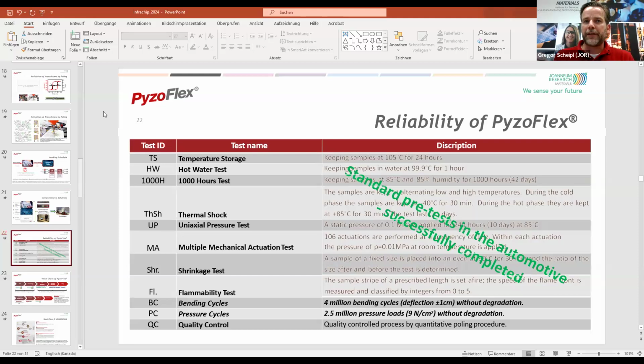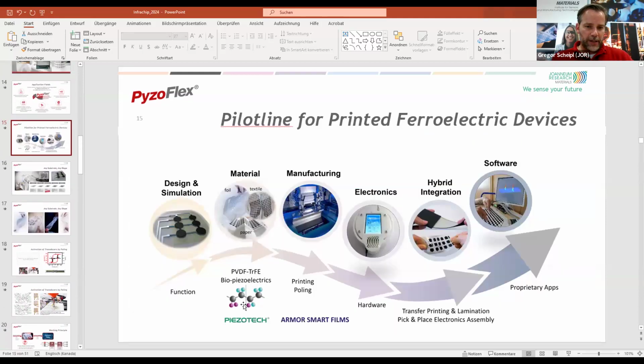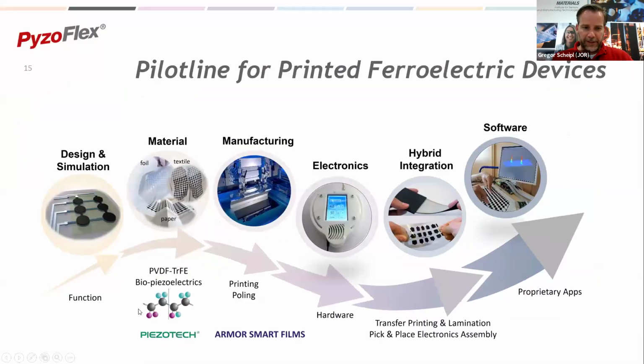but we have an upper temperature limit of 135 degrees working temperature, and I think I can show this here. Here you have this PVDF-TrFE molecule, and I explained that after the printing we have to carry out the poling in order to give them this preferred dipole orientation, and by exceeding 135 degrees for a certain period of time, this preferred orientation flips again and becomes statistical again. It's a reversible effect, so you can do repoling, of course, but it's a material intrinsic property which we have no influence on.